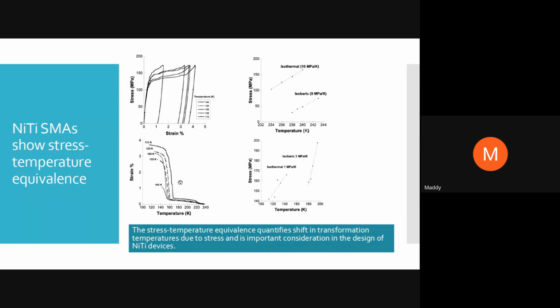So when you plot that on the right hand side, you will see the stress versus temperature plot. You can see that there is a specific linear relationship, which probably may not be actually linear in the strictest sense, but for all practical purposes, right? You can see that there is a linear correlation, and this kind of tells you how much of a shift or how much of stress you can expect with a 1 degree shift in temperature and so forth. So that's why this is extremely important.